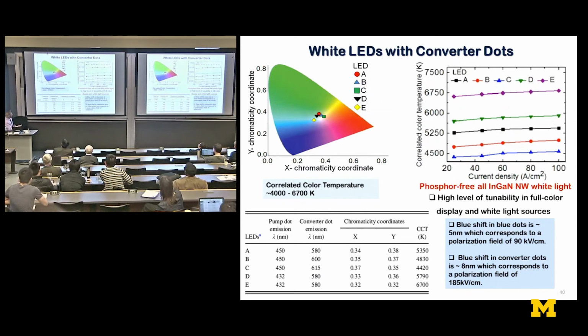And you see the extreme stability also of these correlated color temperatures with pumping, and that is because of the low polarization field.